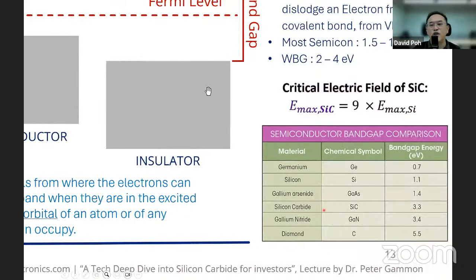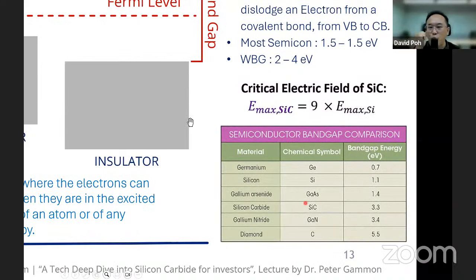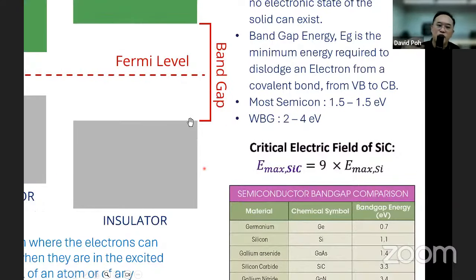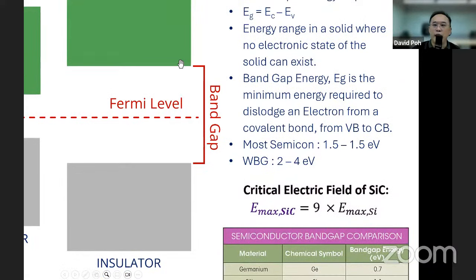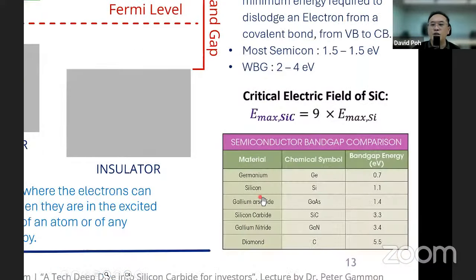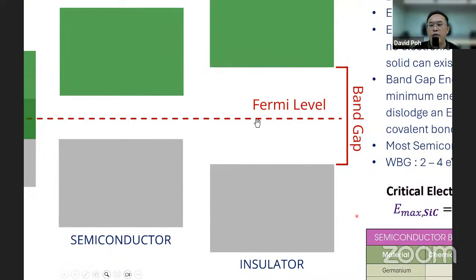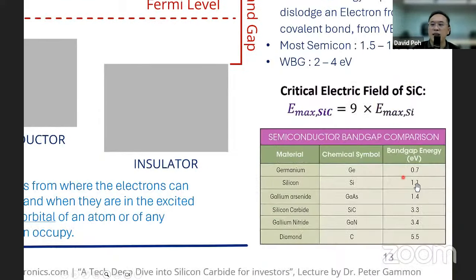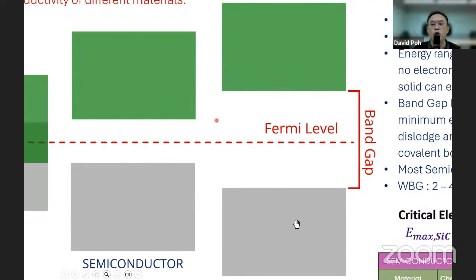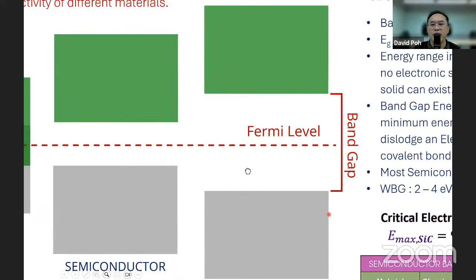This is the band gap energy, the energy that is required to excite an electron from the valence band to a conduction band. Now you can see here, actually, silicon has very low band gap energy. So for silicon, this band gap is very, very narrow. Germanium has the lowest, but silicon is very near. On the other hand, diamond has a very huge band gap energy of 5.47 eV to be exact. So diamond has a very wide one, which is very close to an insulator, which does not conduct electricity, right?